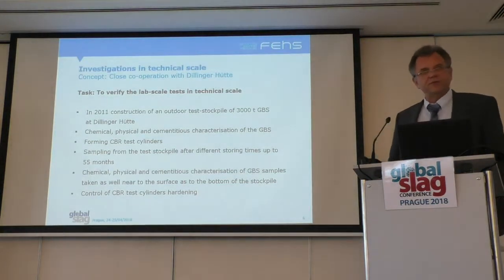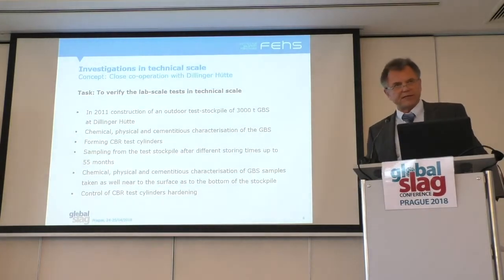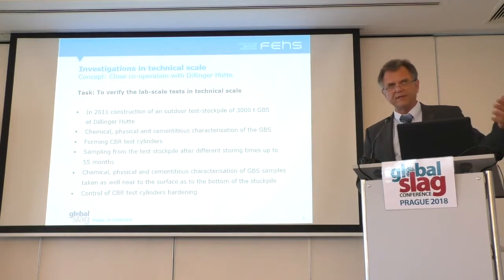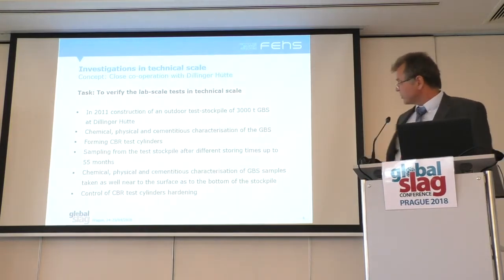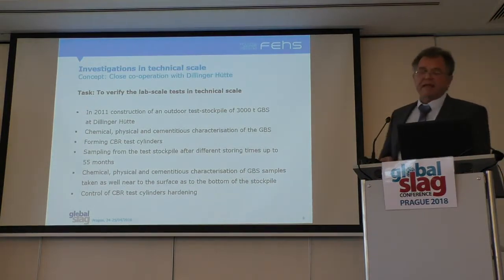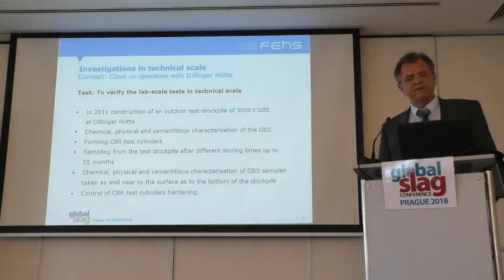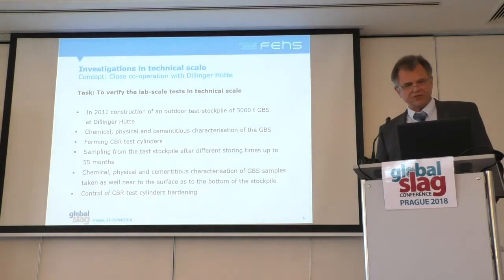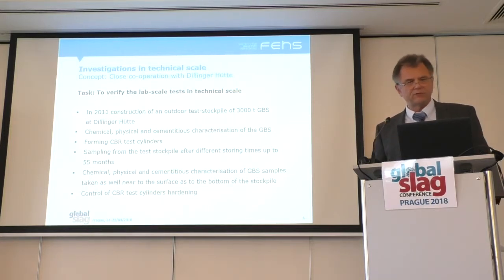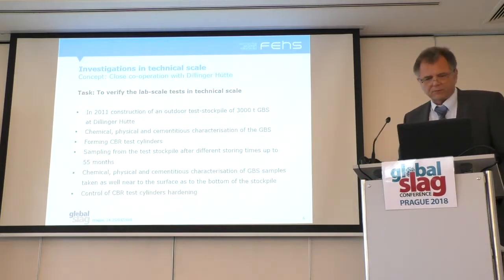In close cooperation with Dillinger Hütte, we then started a project because the colleagues said, okay, that's very nice, it's lab scale results, but our customers, our cement industry customers, asked the same question regarding technical scale. So we developed a project, and Dillinger Hütte started in 2011 to create a stockpile of 3,000 tons of compacted GBS. We made all chemical, physical and cementitious investigations in our own labs. We also formed CBR test cylinders in order to follow the hardening process. And then from time to time we sampled GBS from the bottom and also from the surface of the stockpile.